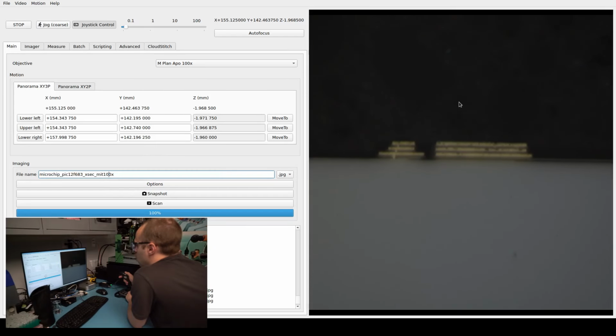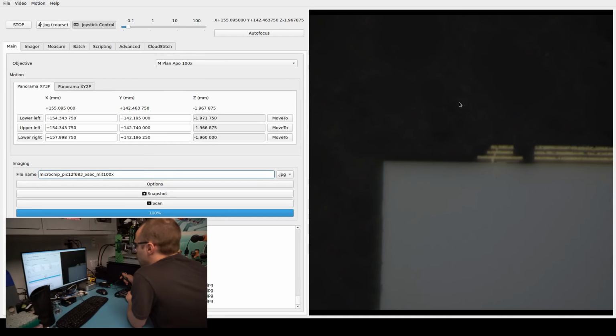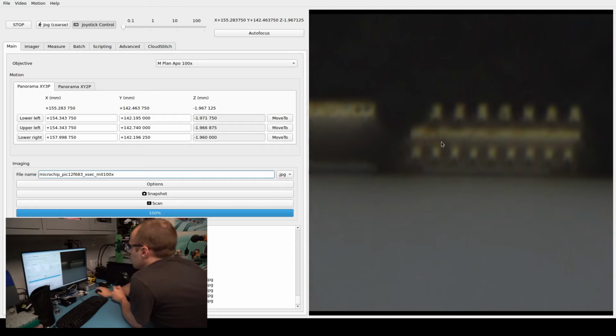Moving up to the top left corner, now we're at the seal ring. This is the periphery of the die and makes sure all the metal layers are firmly anchored and we don't have any delamination. There's a little bit of a space to the left so that the saw can have a little bit of tolerance for positioning and we don't risk cutting into the seal ring if the saw is slightly misaligned during dicing. And there's clearly poly, then 1, 2, 3 aluminum metal layers.